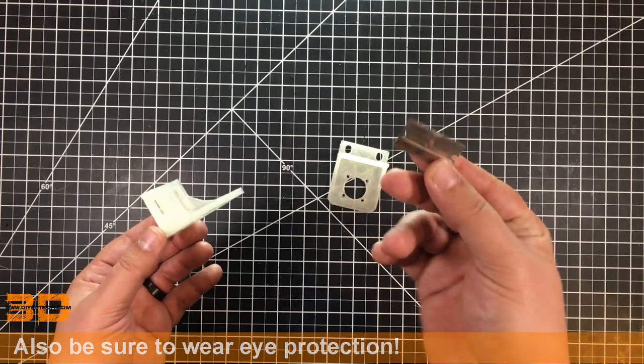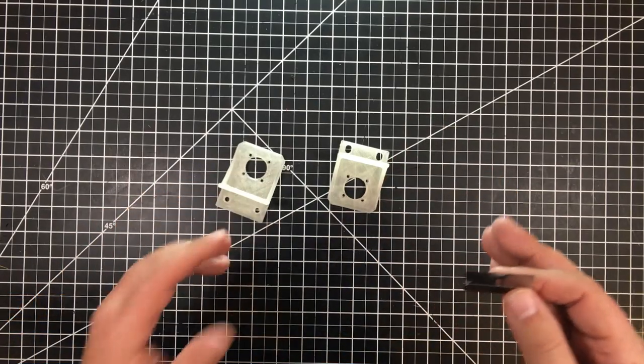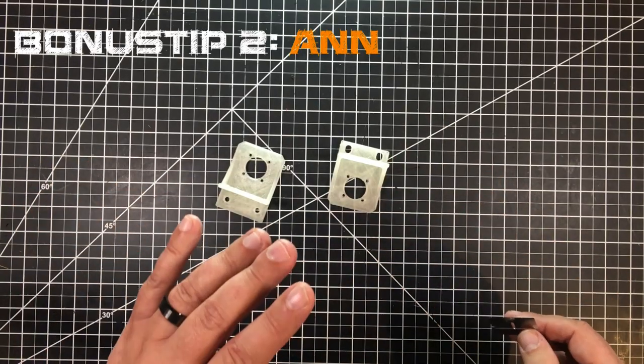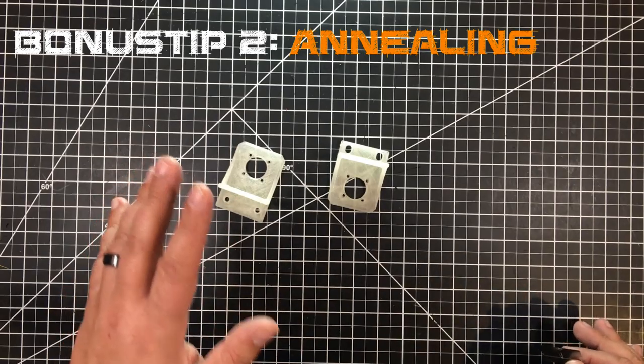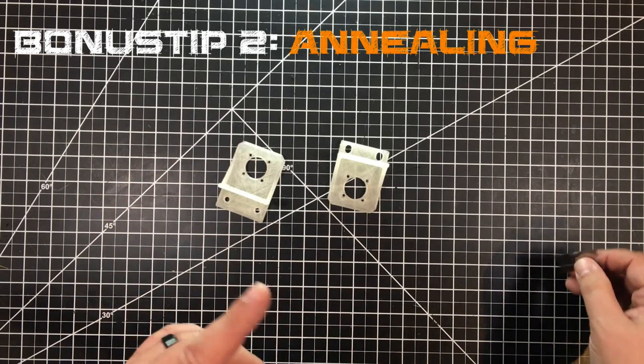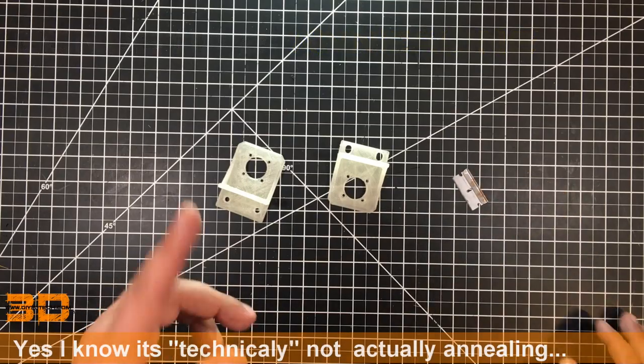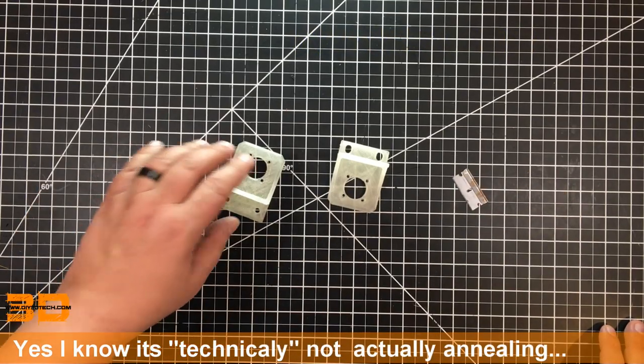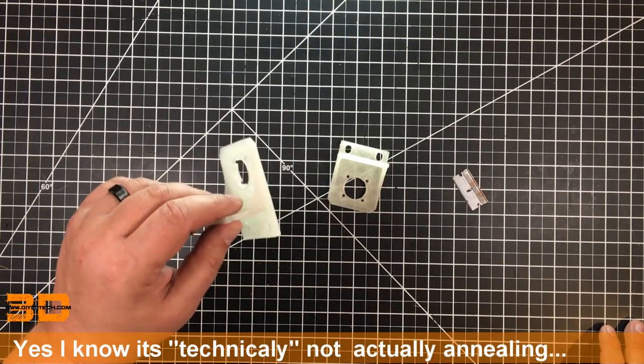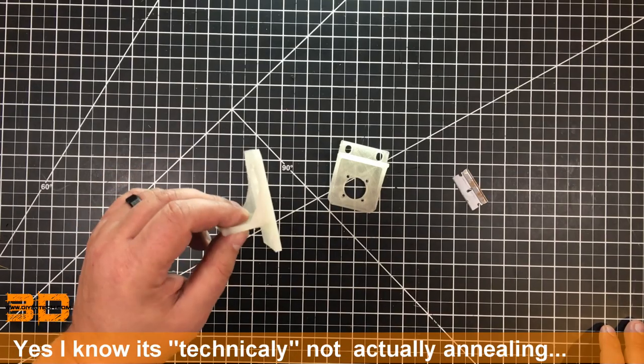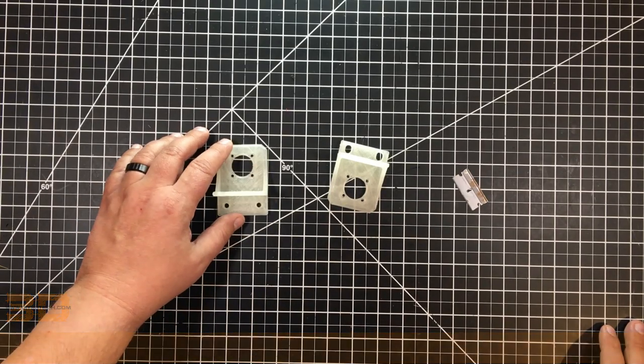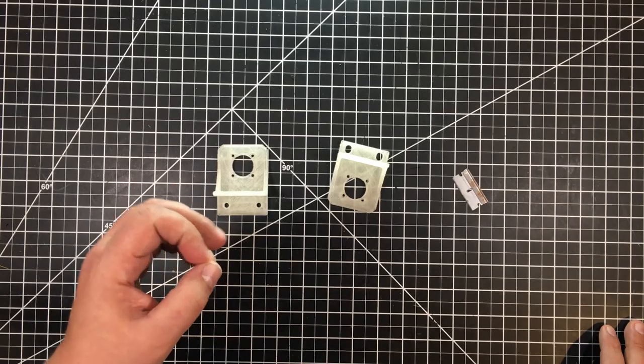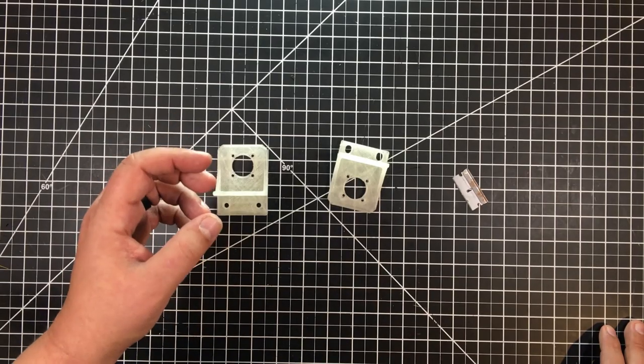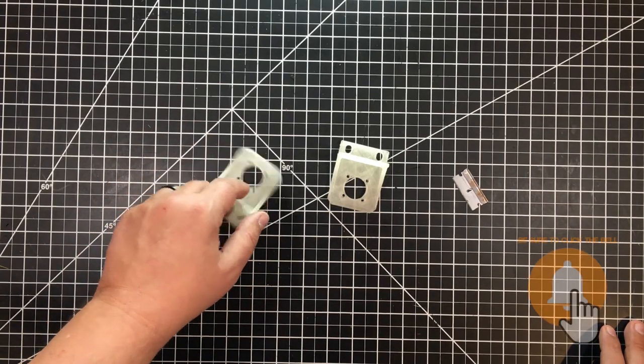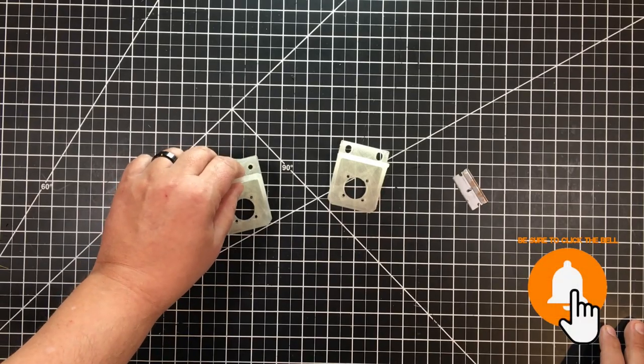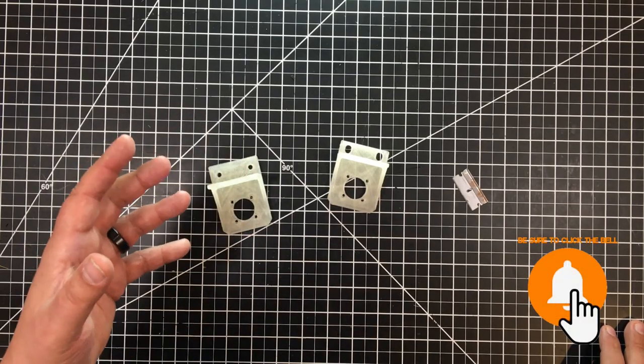This is sharp. So the last bonus tip, and this is optional, but again, it works very well, and I'll be doing some more on this in the near future, is annealing these parts, putting them in an oven at about the glass temperature of whatever plastic you're using for about 45 minutes to an hour. What that's going to do is really allow those layers to set up together, and you will get a super, super strong part.